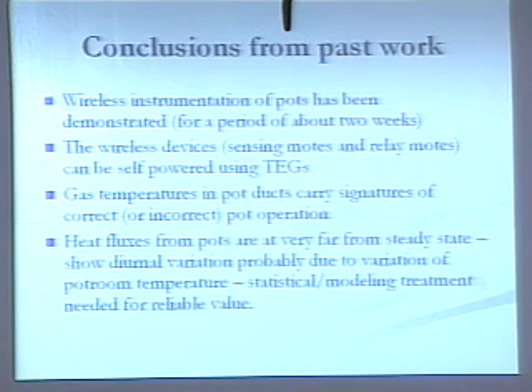Okay, so what are our conclusions from our past work? Well, we've demonstrated that wireless instrumentation of these pots works, and we've done that for a period of about 2 weeks. Wireless devices, the sensing nodes and the relay nodes, can be self-powered using thermoelectric generators. The gas temperature in the pot does carry signatures for correct or incorrect pot operation. And the heat fluxes from the pots are very far from steady state. They show a diurnal variation, probably due to variation in pot room temperature. And we need some statistical or modeling approach to give reliable results.